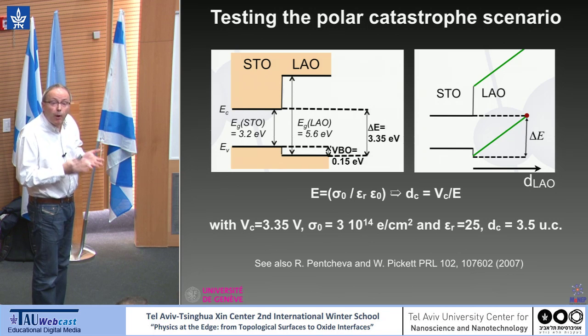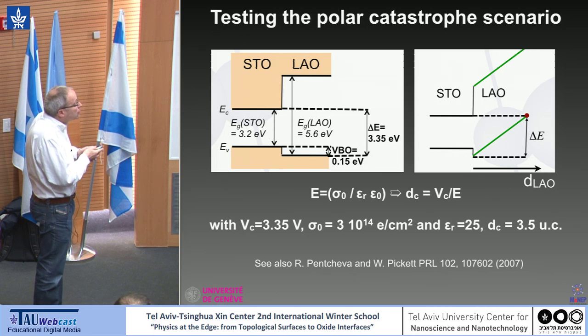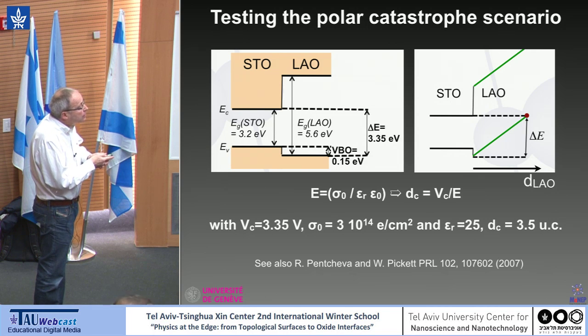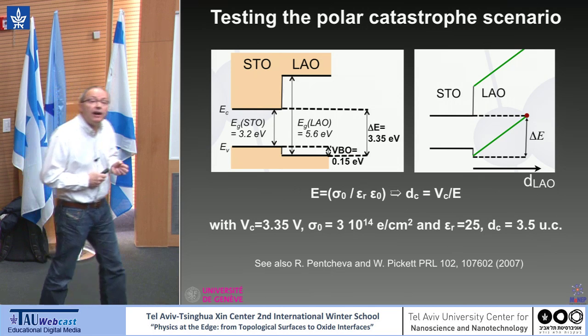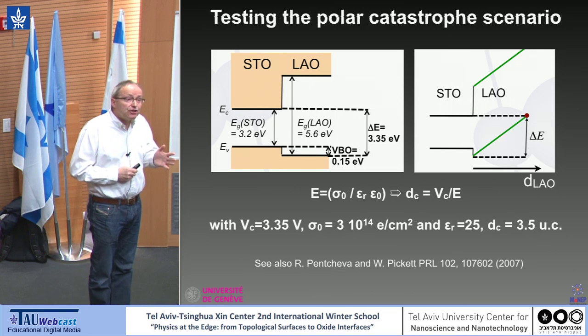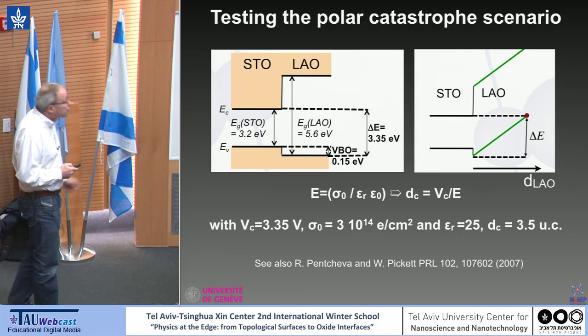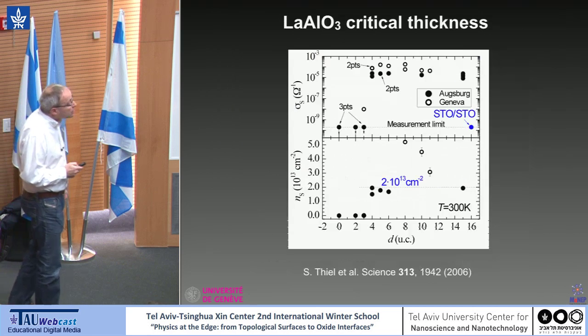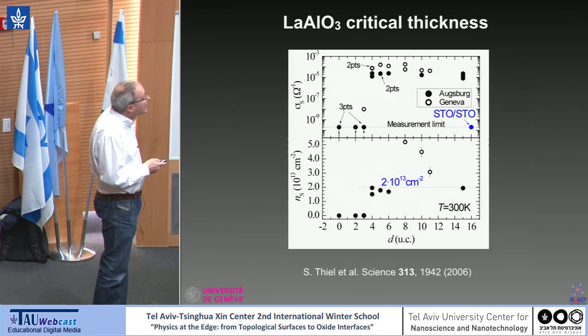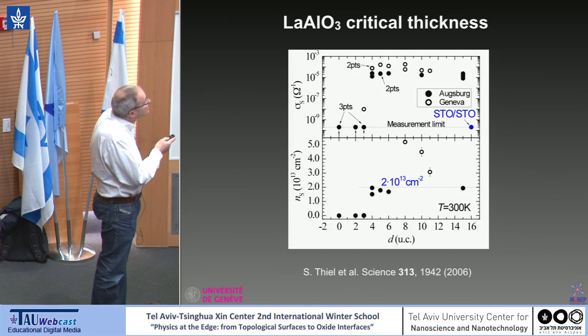So this is really a one-line calculation, and if you do this calculation, you find that the critical thickness is 3.5 unit cells. So the prediction is simple. Below 4 unit cells, the system should be insulating, and it should be conducting above. And this was observed first in the group of Jean-Marc Triscone. You see here the results.